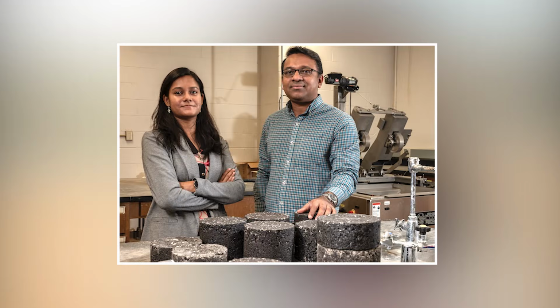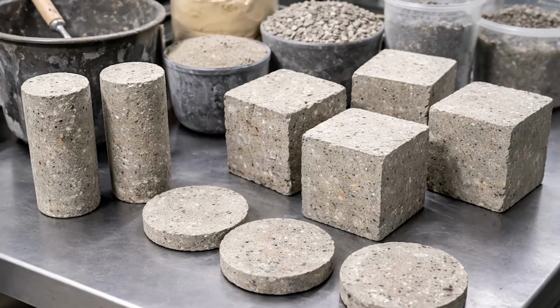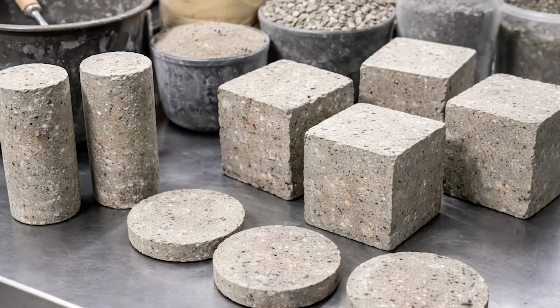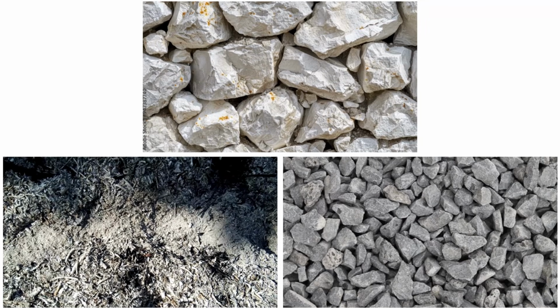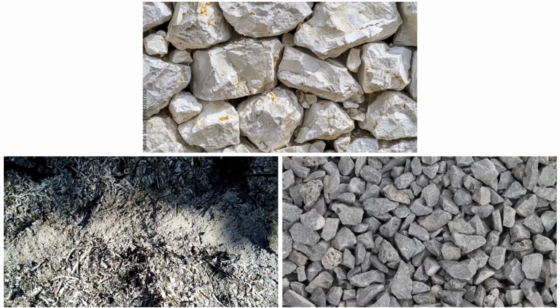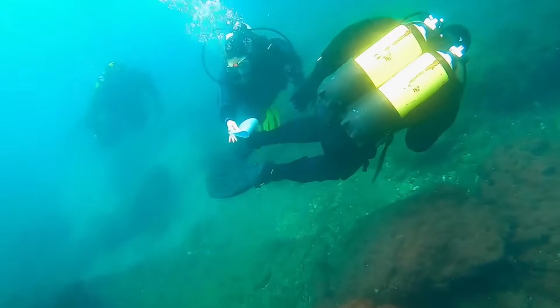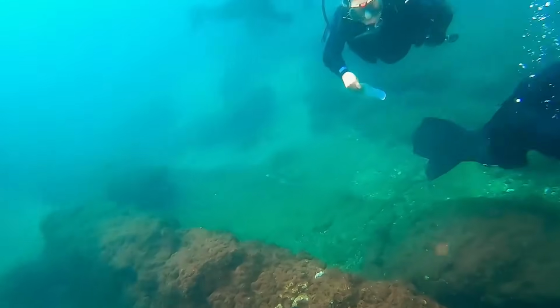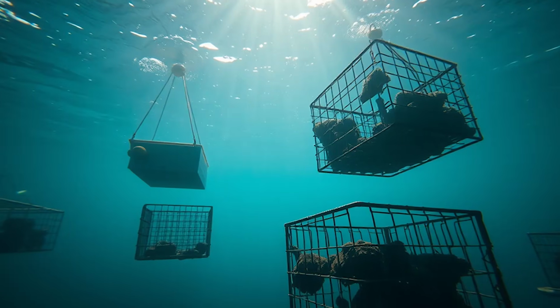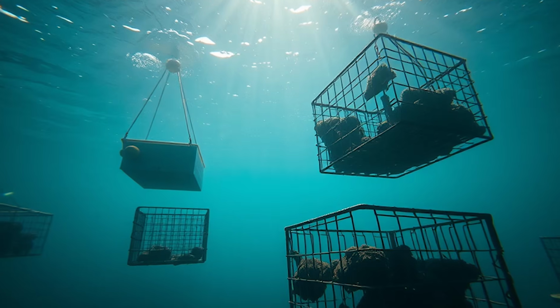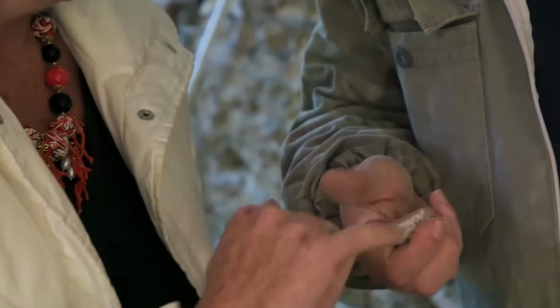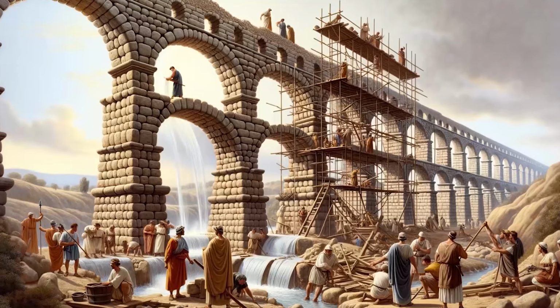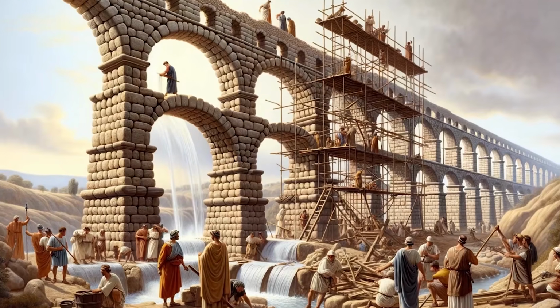Civil engineer Warda Ashraf at the University of Texas at Arlington has already developed experimental concrete mixtures based on this principle. Her team created cylinders, cubes, and discs using Roman-style proportions of lime, ash substitutes, and aggregates. The samples were placed in cages and submerged in shallow water in the Gulf of Mexico. After 1 year underwater, the material had grown significantly stronger. The team celebrated the results. The ancient engineers who built the Roman Empire would likely have approved.